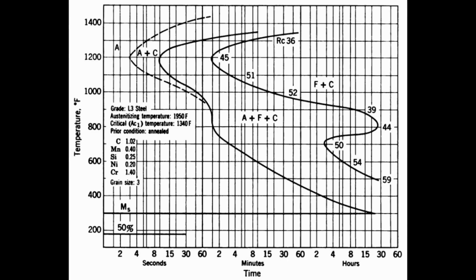Now, I mentioned that the austenitizing temperature is also important, so here's another TTT diagram for L3 steel. L3 is essentially the same thing as 52100, but with a small vanadium addition, usually around 0.2% or so, which helps control the grain size. This TTT diagram, they austenitize the steel at 1950 Fahrenheit, much higher than the 1550 in the prior diagram. And you can see that a couple important changes occurred between the two diagrams.